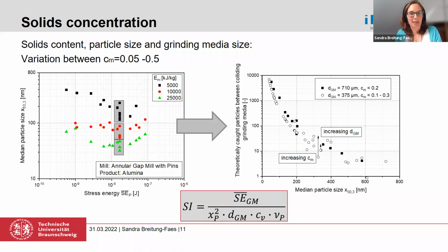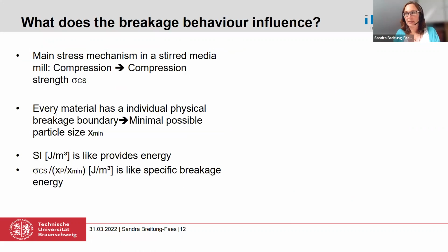And I realized it in the way that I took this calculation for the theoretically caught particles, skipped all the constant values you see like pi and so on when you calculate volumes of spheres, and put in the values which were interesting for us into this stress intensity. And these are the grinding media diameter, the product particle size to the square, and the solids concentration. And still you see here the energy transfer coefficient of the product. So I thought, okay, with the stress intensity, I created a value which is more or less reflecting something like the energy which is transferred to the product.